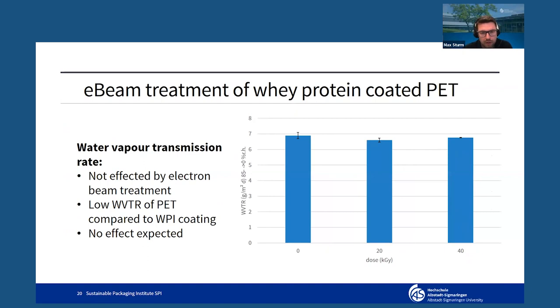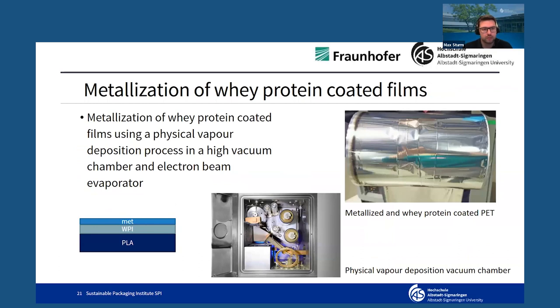As we saw before, for the PET and PE, there was no meaningful or significant impact, as the whey protein coating itself contributes very little to the overall water vapor barrier properties of this multilayer structure. So we achieved very good results also with the e-beam treatment, but the whey protein coated films are still not applicable for high barrier applications.